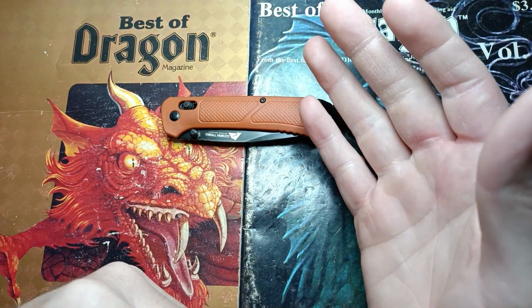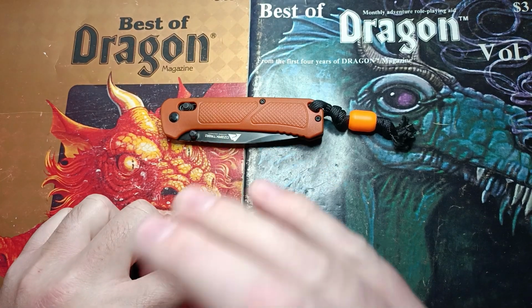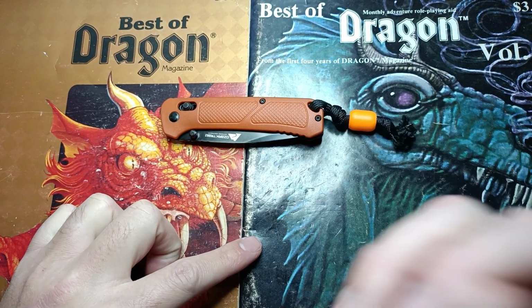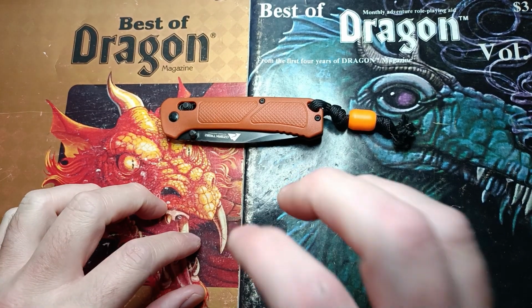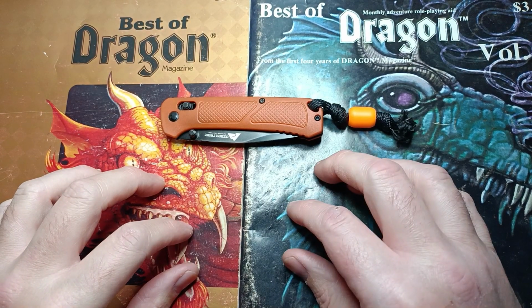One of the guys I've seen in my live streams, he does some videos, he snapped his and we looked at the grain structure on his, and that grain structure looked really, really good. Light gray, very powdery, very fine grains. It looked good. I am sure I'll get similar out of this if I do it. I just don't want to snap this yet. I don't think I'm done with it. But yeah, as I said, if you get a chance, look at the grain structure. It's not like you're really losing much.